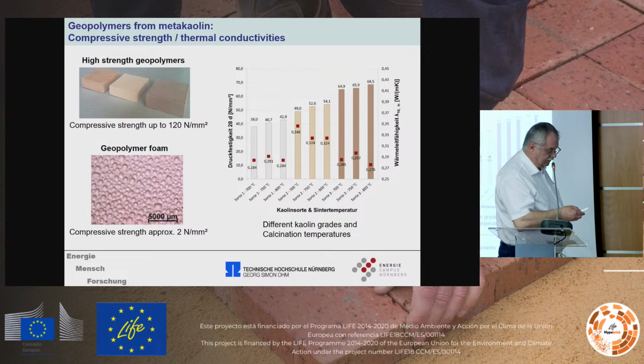Here you see reactions we did. Here we have the compressive strength, and here we use 3 sorts of kaolin, and we burned it to metakaolin with 700, 750, 800 degrees with 3 sorts. And here you see the compressive strength. You go up with the temperature, so you have a better compressive strength. You see this here. And here you see the thermal insulation.